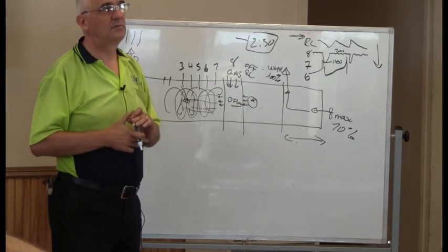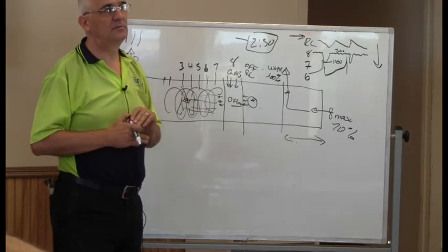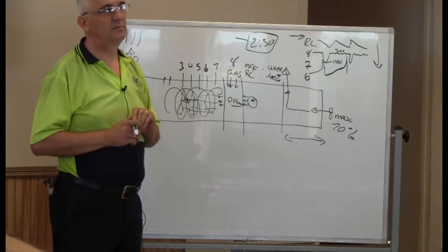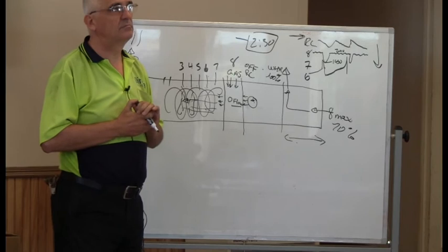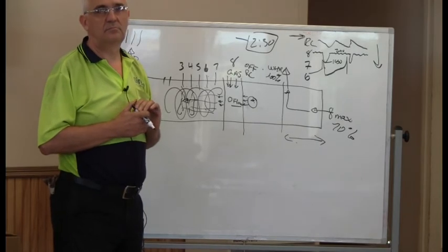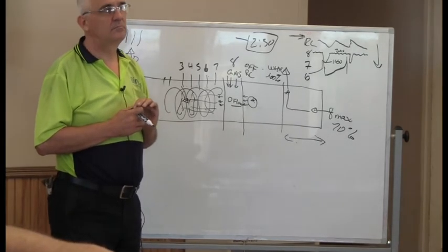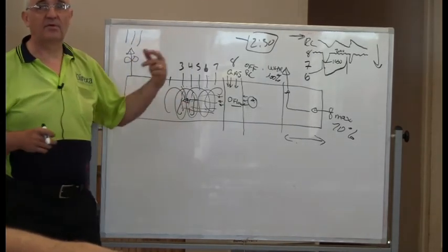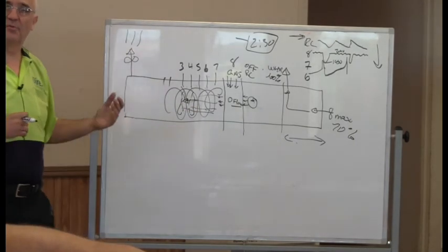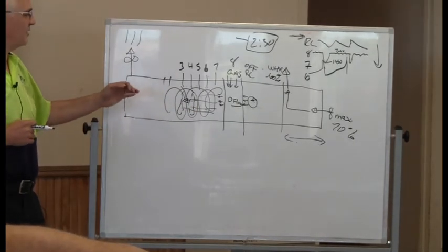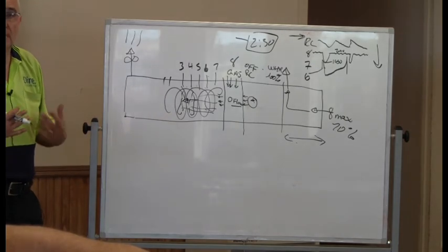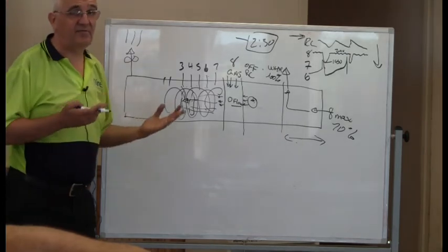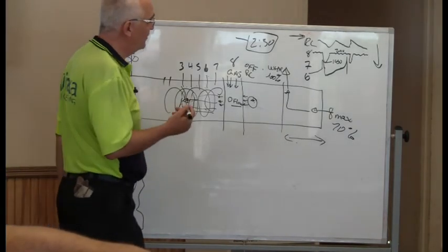Before we had it dropped to like 19% output. And I wish I had a number to put with that. But right now the number that we're doing is like 29, 30, 31, somewhere in there. I have to go look. Because you still have to pull from here, your side burner, your top burner, you still have airflow to pull, so it can't be cut too much. Me, the guideline I have when I flash, there are 2 spots I'm looking for.